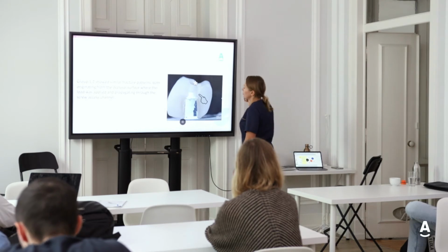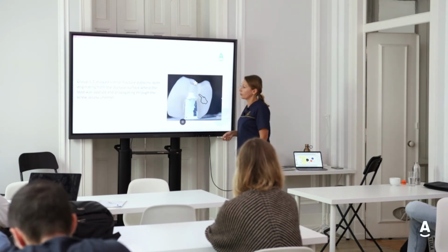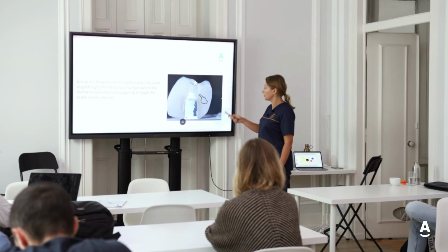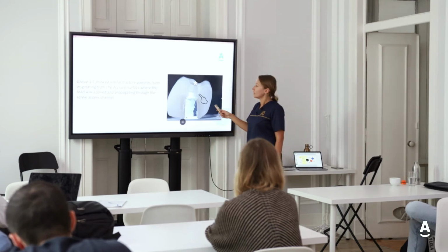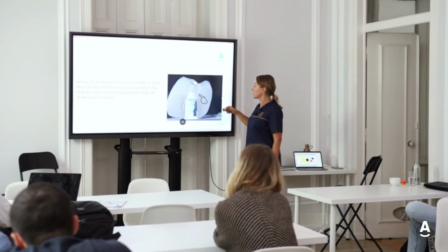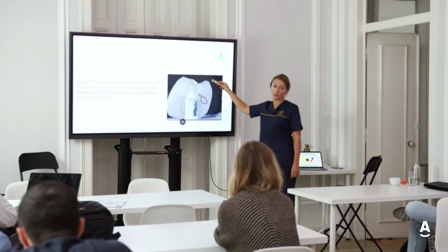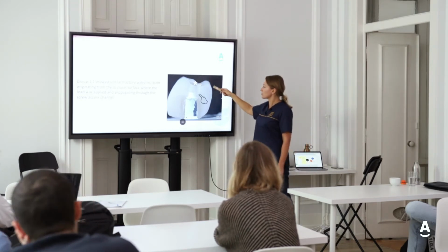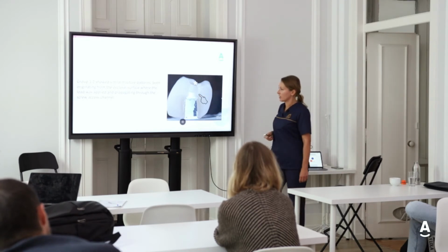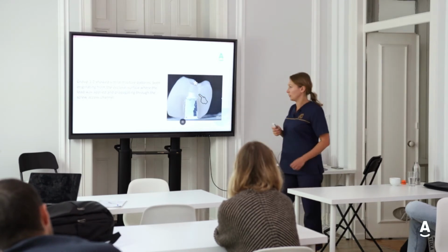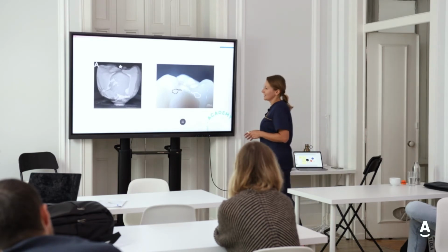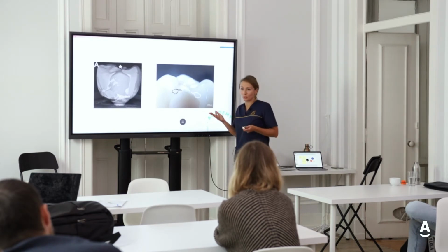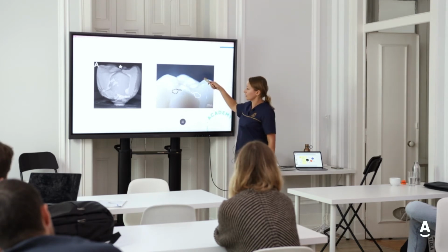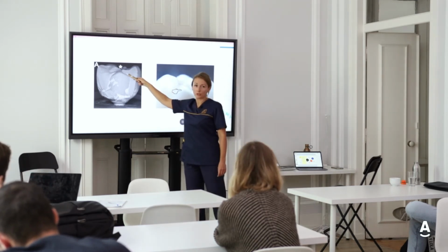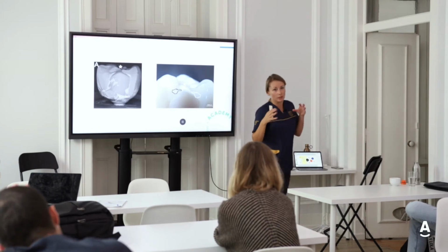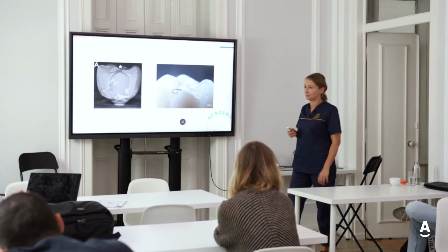So the pattern of the fracture for both group number 1 and 2, the screw retained crowns, was always similar. The fracture was beginning on the occlusal surface and was propagating through the screw axis channel. While it's very interesting because in the third group, the pattern of the fracture was normally the crown fracturing and the abutment was keeping intact.